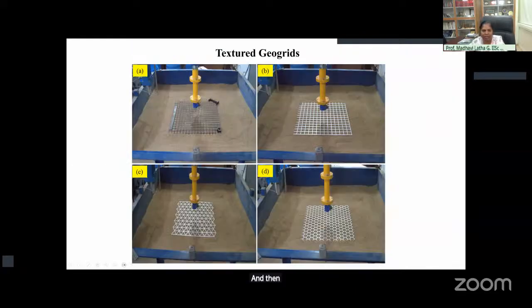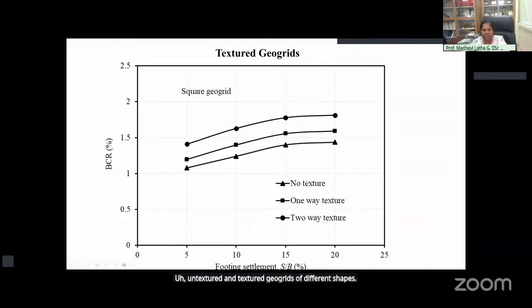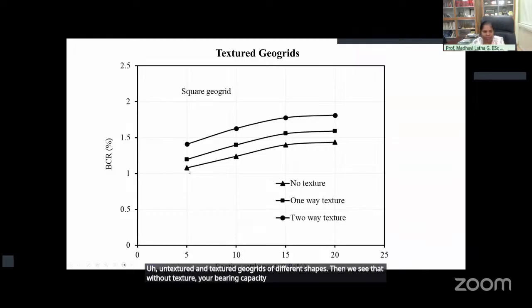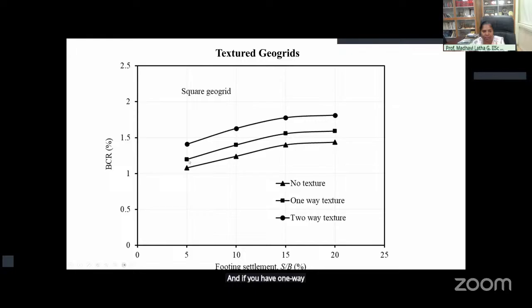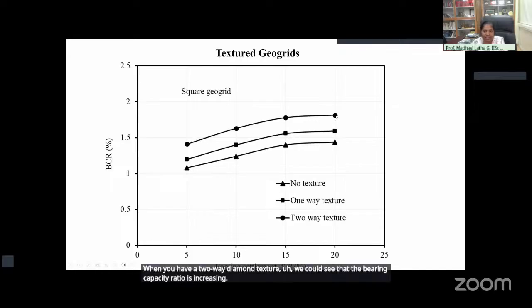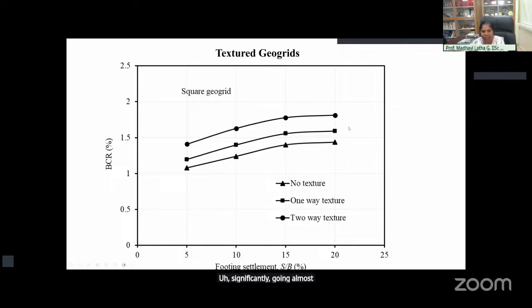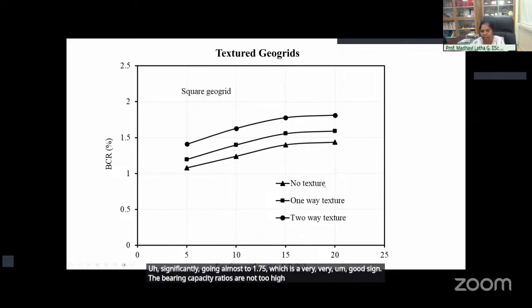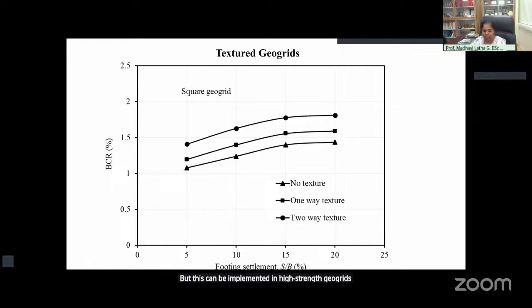And then when we did plate load tests with reinforcement in the form of untextured and textured geogrids of different shapes, we see that without texture, your bearing capacity ratio is varying from something like 1.1 to 1.3. And if you have one-way texture, you can further increase it to up to 1.7. When you have a two-way diamond texture, we could see that the bearing capacity ratio is increasing significantly, going almost to 1.75, which is a very, very good sign. The bearing capacity ratios are not too high here because of the low strength geogrids that we're using. But this can be implemented in high strength geogrids as well with other manufacturing techniques.